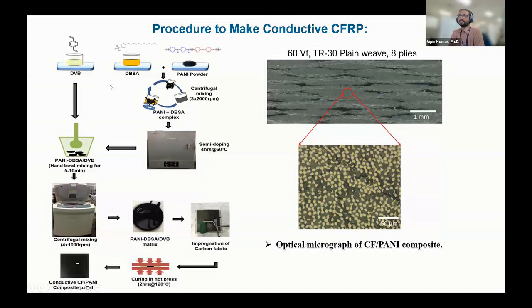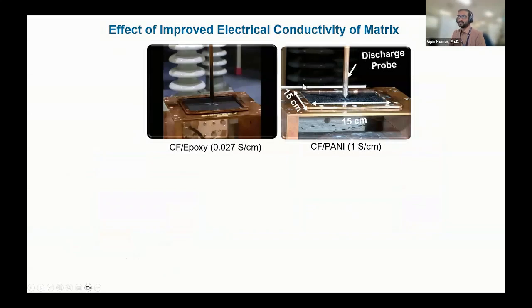And now if I have a resin system, I can impregnate my fibers to make a final laminate. Although my carbon fibers were electrically conductive, the resin was not. I have put the conductive resin between those carbon fibers, so I have a fully conductive network within a composite. So what will happen? Let's see.